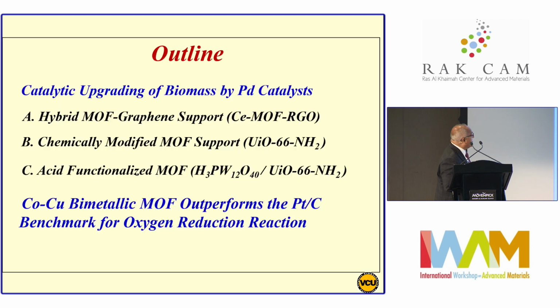So the plan for my talk is I want to give examples of using MOFs first as a catalyst support and what kind of modifications and tuning of catalytic properties you can use by changing the support, not the catalyst itself. And this will be done through catalytic upgrading reactions of biomass using palladium catalysts. But the MOFs will be the support catalyst. I'll give 3 examples of that. And finally, second part, I will talk about MOFs as a catalyst. So this is a cobalt-copper bimetallic catalyst that can actually surpass the very famous and well-known platinum-carbon catalyst for oxygen reduction reaction.